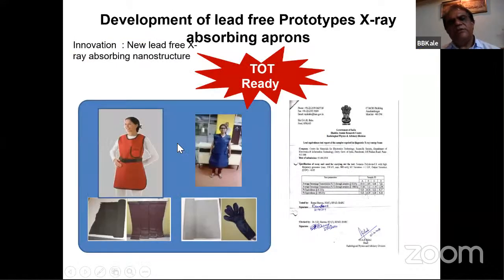Then this is a nano coating developed by C-MET. See, generally this apron contains lead, because lead is a good X-ray absorber. Whenever you go to an orthopedic doctor, they wear this kind of apron, because if they want to work under X-ray systems, they use these X-ray absorbers. The weight of this apron is 8 kg. Our nano coating is 3 kg. That is the difference. So doctors are very happy with this kind of analysis.